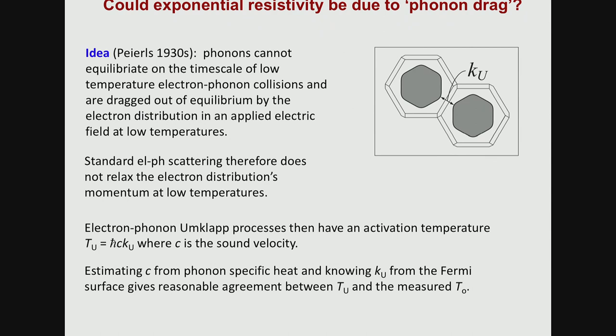So let's imagine that we are dragging our phonons perfectly, so that all of the normal electron-phonon scattering around our Fermi surface just results in dragged phonons and no observable contribution to bulk resistivity, because the phonons just get the momentum with the electrons. Then the first electron-phonon process that you're going to see will be an umklapp one, when the phonon has enough wave vector to scatter you across the zone into the second zone. You can calculate the characteristic energy for that. If you know the gap in k-space and you know the sound velocity, you can then calculate an umklapp temperature. And when we did that and compared it to our measured T naught, it came out numerically very similar.